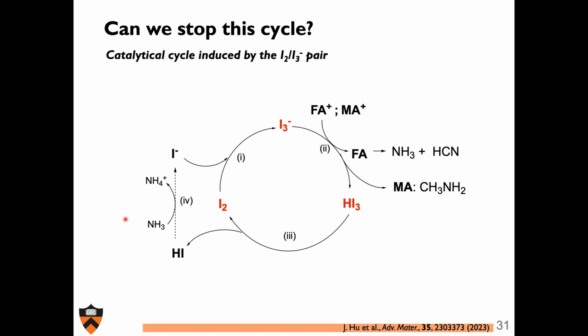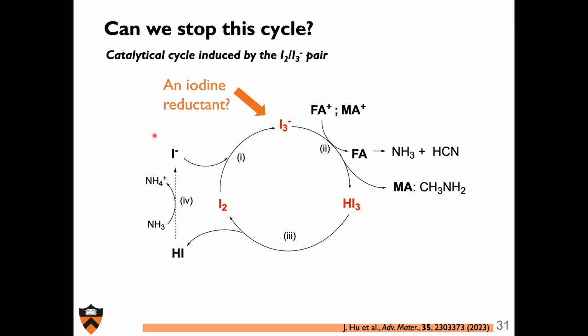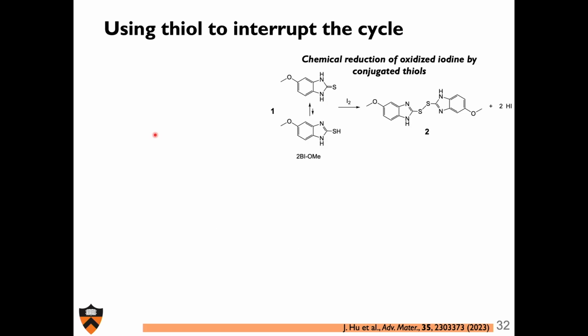So we asked the question if we could stop this cycle. And the most effective means that we saw was, could we put something here, something there that could act as an iodine reductant? So if iodide is ever oxidized, could it just interrupt it? We know there's one, silver, not a good one, because we don't want silver entering the lattice. Maybe there's another system that we could use as an intermediate to, if any iodide is oxidized, push it right back to iodide. And we drew inspiration from biochemical processes where thiols are pretty good reducing agents. What we wanted to do was see if we could use thiols to reduce iodine and then make these disulfide compounds and therefore interrupt this catalytic cycle.